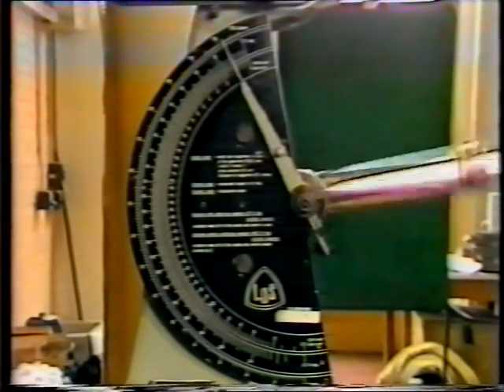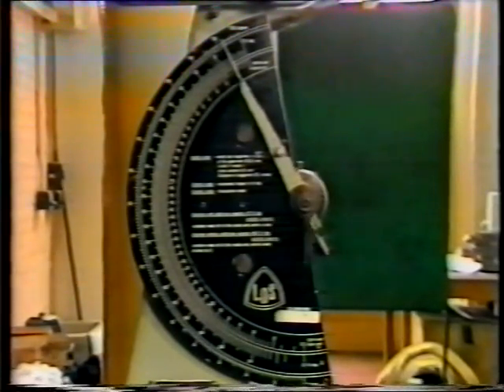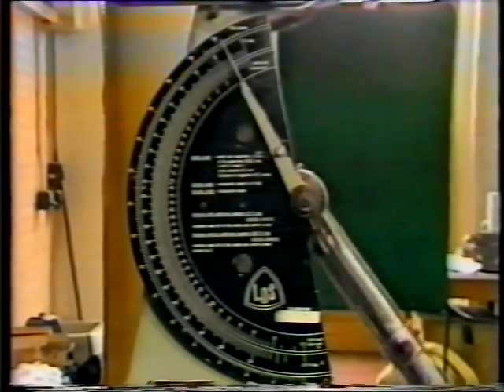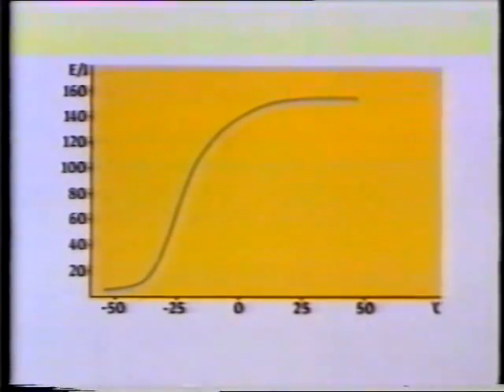This is a very high quality steel. But at this temperature, it's totally brittle. No toughness at all. If we plot the Charpy energy on the vertical axis against temperature, we get a characteristic graph. There's an upper shelf where the steel is tough, and this represents a ductile fracture. Looking at the fracture face, its rough nature is typical of a ductile fracture. Higher magnification shows this more clearly.